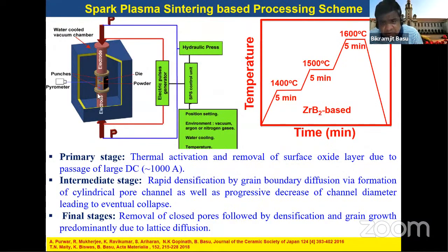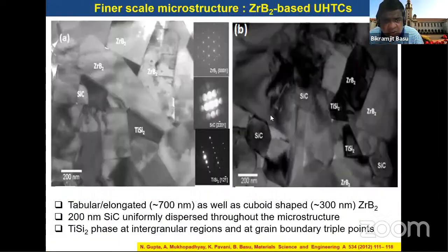In this spark plasma sintering technique, we use a multi-stage sintering technique, where we hold at a temperature which is around 0.5 Tm. Then we increase the temperature, we hold it at a secondary holding temperature, a second hold, before it reaches the final sintering temperature. We have found that this kind of three-stage or multi-stage sintering process essentially allows one to control the grain growth and at the same time enables the achievement of very high sintered density.